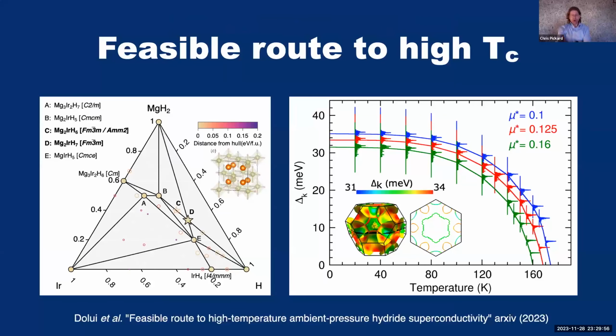So this is the result of some work that we've done in that direction very recently. It's been posted on arXiv just a few weeks ago. It's been in collaboration with my postdoc in Cambridge, Kapildeb Dolui, and others, where we have repeated that high throughput random structure search for a wide range of, in this case, ternary phases rather than binary hydride phases at ambient conditions. We are only now interested, actually, in superconductors at 0 GPa. And so what we do is very extensive searches across wide ranges of compositions to pick out stable or close to stable phases, and then compute for as many as possible the superconducting transition temperature.